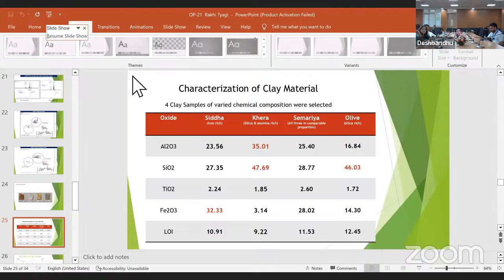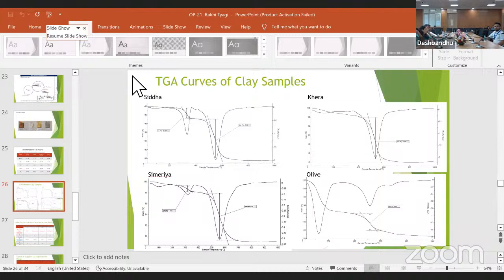The Simaria sample has alumina, silica, and iron in comparable amounts, while the sample termed Olive was rich in silica. Now, this is the TGA curve of the selected clay samples.